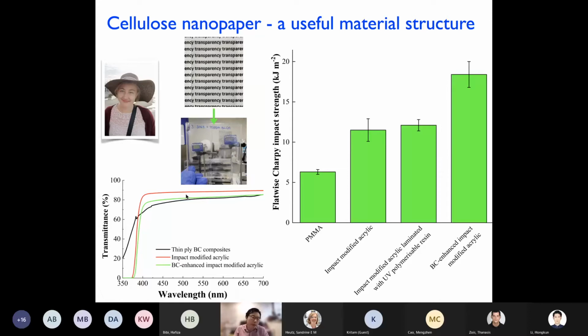The interesting bit about this is that if you were to look at the Charpy impact strength of this product here, just with the introduction of the cellulose nanopaper into the final transparent composite, we're able to increase the impact performance by 60% relative to the impact properties of impact modified acrylic, bearing in mind that impact modified acrylic is already designed to have high impact performance, and we're able to push that value further up by 60%, all with just introduction of 0.2% of this cellulose nanopaper into the final product, just 0.2%. And that allowed us to push the performance up to almost 20 kilojoules per square meter, compared to impact modified acrylic of about 12 kilojoules per square meter of impact strength there.